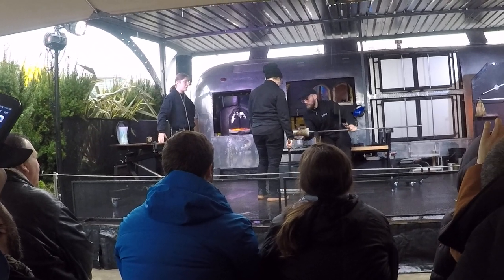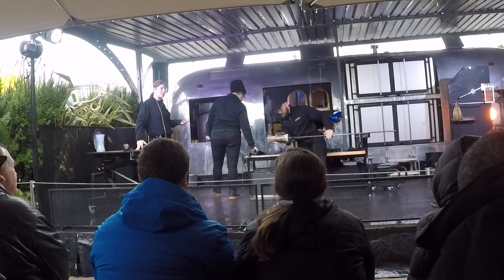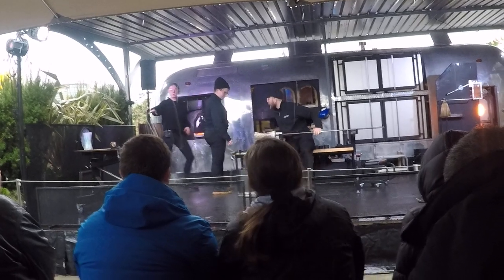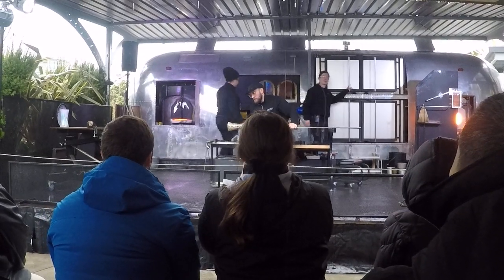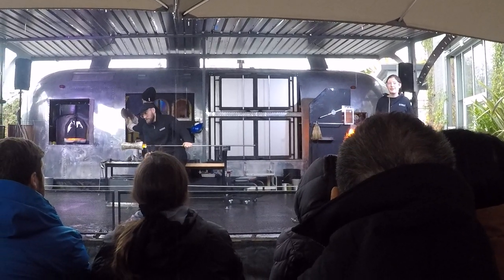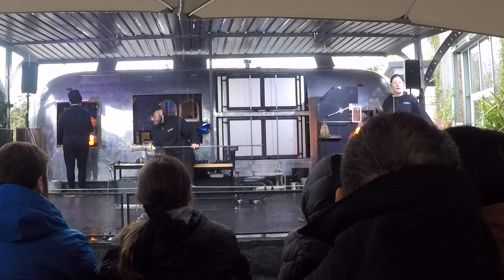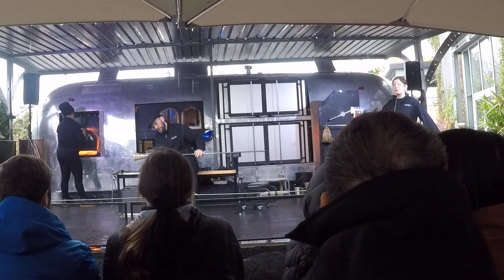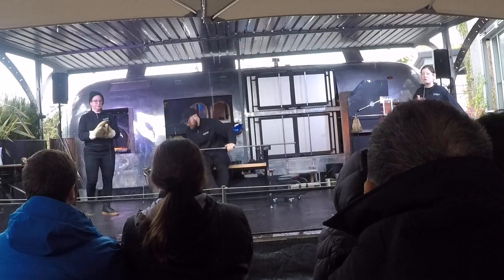We use organic beeswax — but that's because we're out here in Seattle. I'm using the newspaper again just to shape and cool the glass. We're very close to being finished with this shape. We can't let it air cool on the marble, or it's going to crack within a few minutes. So we have to put it in this silver box called the annealing oven, which is holding all the glass from today at 950 degrees Fahrenheit — hot enough that the glass won't crack, cold enough that it won't change shape. At the end of the day we'll start what we call the annealing cycle, which is a very slow, controlled cooling process.